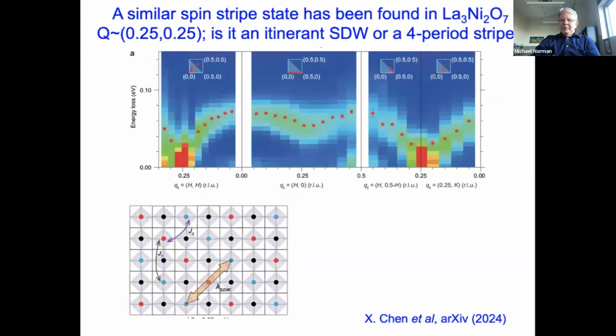So very recently, this paper came out on the arXiv. What they're seeing in the 327 material looks commensurate. It's a 1/4 state, looks like a 4-period stripe, but the resolution is somewhat poor. And why I say this is, in 214 nickelate at 50% doping, you do have a tendency to see slight incommensurability, but it looks pretty much similar to a 4-period stripe state.